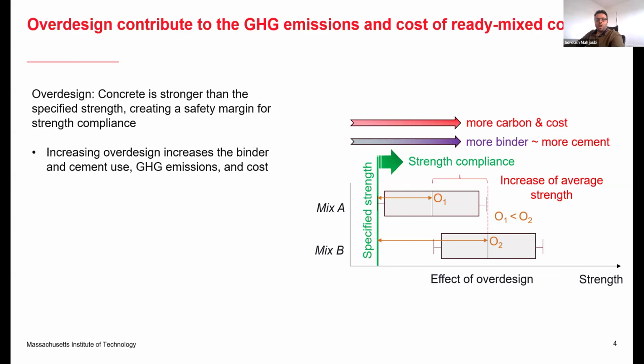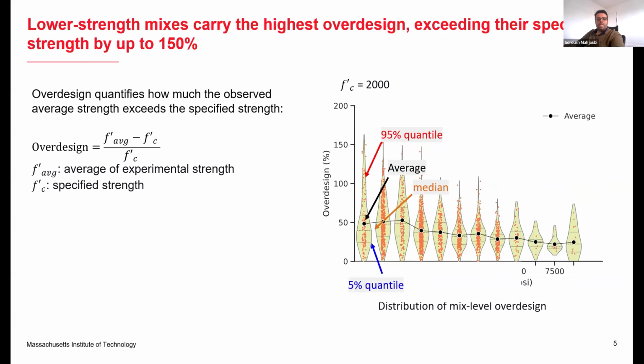And this diagram shows two concrete mixes, Mix A and Mix B, where Mix B has greater over-design than Mix A, represented by orange markers O1 and O2, showing the relationship between the over-design levels and environmental impact. Now let's examine the quantitative impact of over-design across different strength classes. We define over-design as how much the observed average strength exceeds the specified strength using the formula shown here. And this violin plot shows the distribution for a 2000 PSI mix where the average over-design exceeds 50%, with the 95th percentile reaching about 120%, and the median sits around 50%.